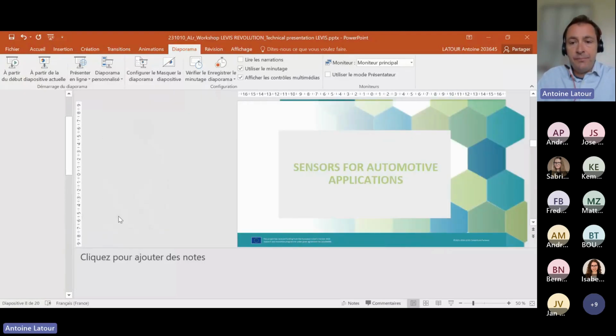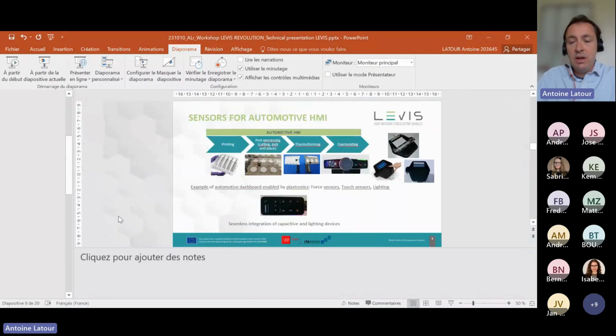So concerning the sensor for automotive application developed at CEA, it's more or less the same process as the one presented just before, or presented also by Farplas. The main difference is that we are using printing processes. We use a screen printing process to print conductive lines, piezoelectric transducers, force sensors, humidity sensors, for instance. And then, as I mentioned before, we can use a pick and place device to add functionalities such as LED or microcontroller.